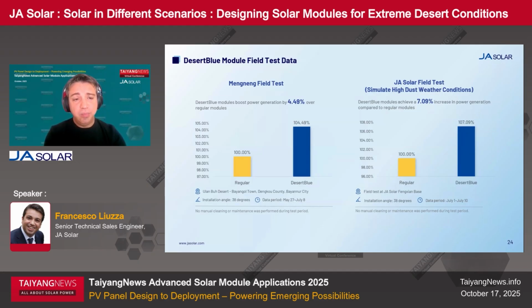You can see how the DesertBlue is boosting power generation by around 4.5% compared to regular modules. And on the Fengshan base, in specially simulated high dust weather conditions, we achieved a 7% increased power generation compared to regular modules. The hypothesis is that no manual cleaning or maintenance was performed during this test period. So we compared to a condition where no maintenance and cleaning was performed, especially in this test. So please feel free to contact us to have more information on the field test. These are the proof that DesertBlue modules and how JA is approaching the new scenarios can really affect the value of the project and performance.